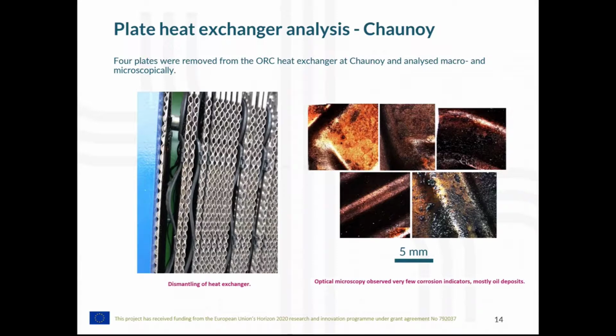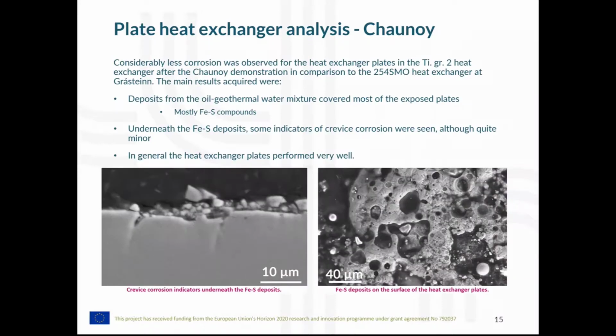minor corrosion indicators, but mostly you can see the black oil deposits, which are to be expected from such an oil geothermal water mixture. And we observed considerably less corrosion on the heat exchanger plates in the titanium grade 2 heat exchanger at Chaunoy.